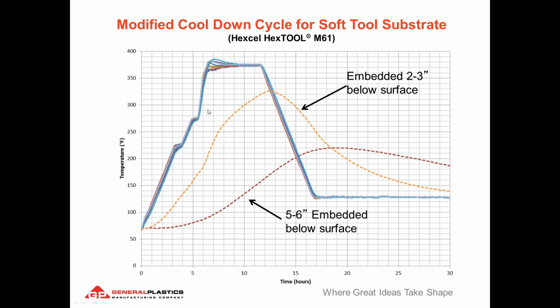And what we offer customers now is different temperature profiles. In other words, what temperature is the foam really at when a customer provides what their ramp-up schedule is. Now, this type of profile on a very large tool would likely cause the tool to show surface cracks and potentially not be reusable or cause the need for patching afterwards. So for one-time prototype use, you want to get through your oven or autoclave quickly. You can cool it at the recommended rate for your graphite composite on top.